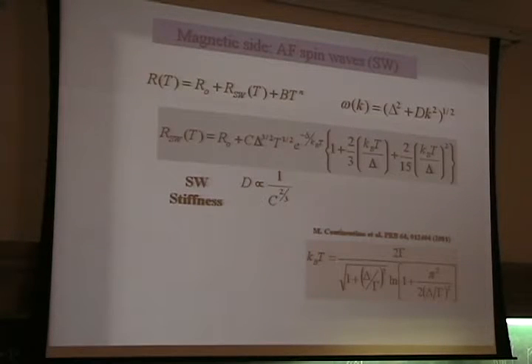Okay? So again, using the spin wave scenario, we can try to fit this resistivity on the magnetic side, and for an isotropic antiferromagnet, the dispersion relation is given by this. Okay, and the resistivity given by the spin wave is given by this formula. Okay, and then we fit our resistivity data, and we can obtain the gap of this magnetic spectrum. And also the Tn is given by this, in the case of a 2-dimensional antiferromagnet, the Tn is given by this relation.